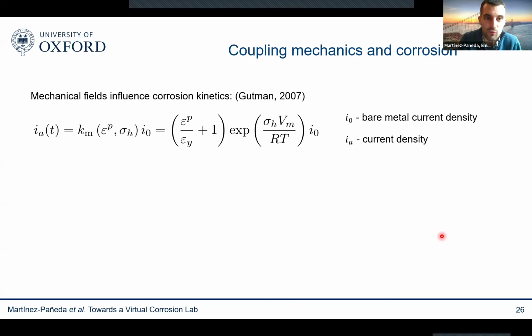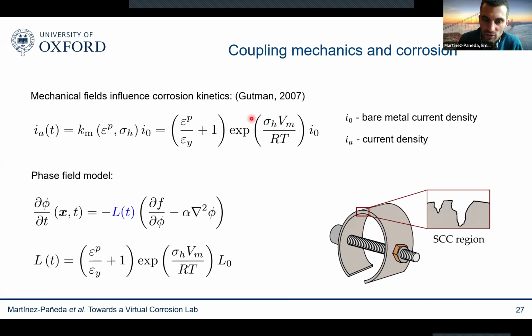The first thing that I want to say is that, of course, we want to incorporate the role of mechanics. We're mechanicians, so we like mechanics. And mechanics can play a role in corrosion in two ways. Mechanics can influence corrosion by first enhancing the corrosion fields. This is, as you can see here, captured by Gutman. So corrosion kinetics, this is the corrosion current density, is enhanced by dislocations and hydrostatic stresses. And because the mobility coefficient is proportional to the corrosion current density, as explained before, we can enrich the description of the mobility coefficient and incorporate this interplay with mechanics. And then, we solve a mechanical problem as well, and we're able to predict what happens.